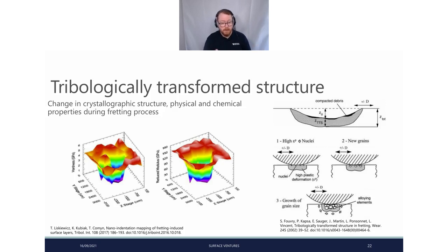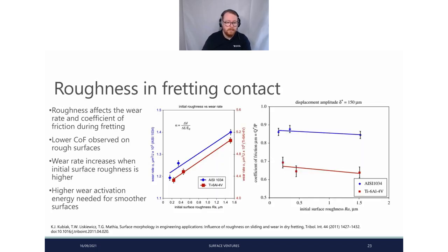how does it transform? One of the easiest ways is to actually measure it. The mechanical properties do change over longer periods of time. You will get oxides forming. These will typically be thrown out of the wear scar, and you will instead get this softer region, and this region where it is not as stiff after fretting.